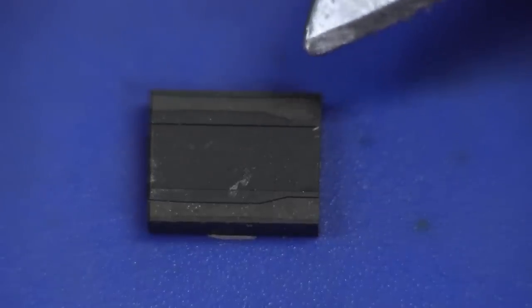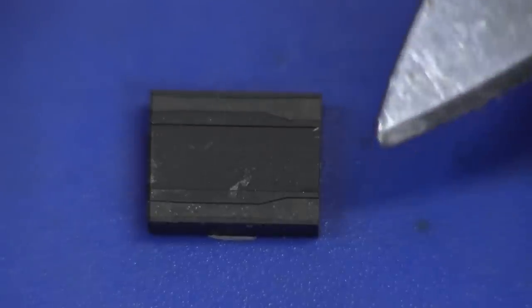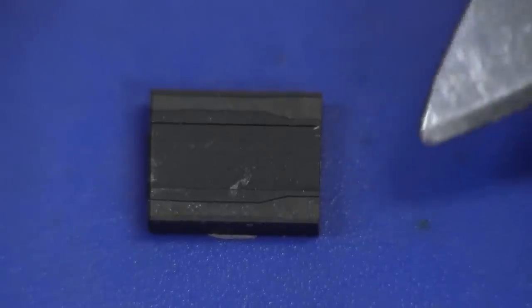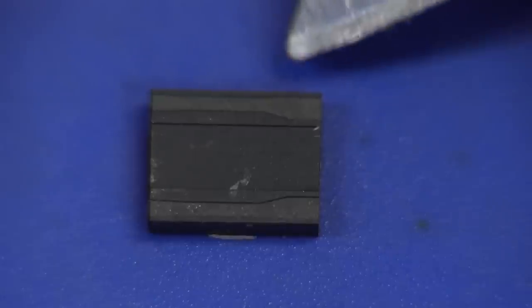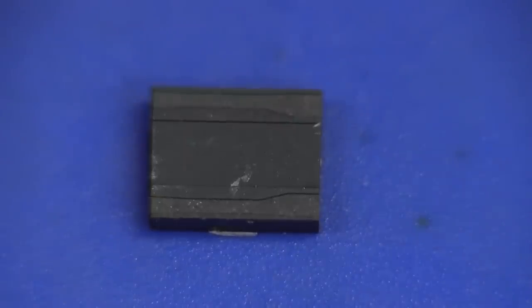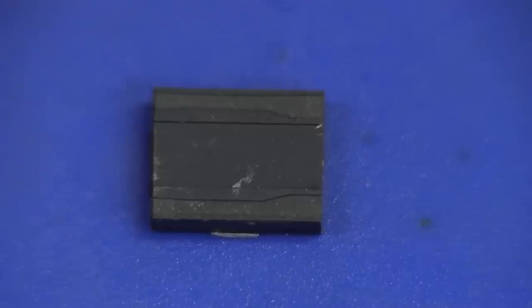can change shape based on the applied magnetic field, very slightly. But because this is a highly precision engineered head, even back then, I mean, the modern ones today are an order of magnitude more sensitive, of course, but even back then, you have to be very careful that when you're writing the ones and zeros to it, changing the magnetic field, it does not physically change shape. And that can work vice versa as well. So any strain on this thing can actually generate a magnetic field, so they can use it as a sensor in that respect. You don't want any of those type of effects in a magnetic recording head, so these materials will be chosen to have near zero magnetostriction effect.